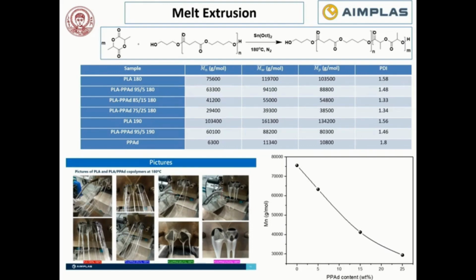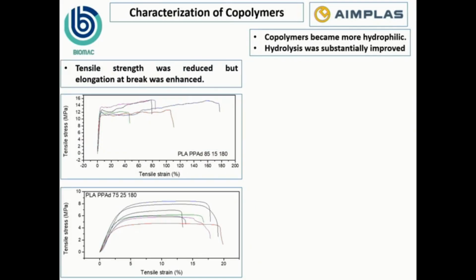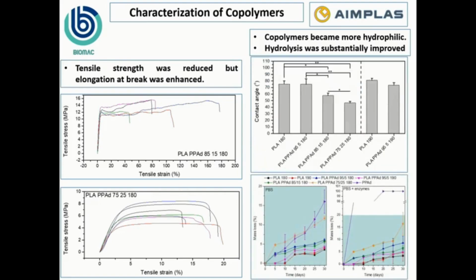In the copolymers, as the amount of polypropylene adipate increases, there is a slight reduction in molecular weight, which was expected, but we succeeded to increase the elongation at break. PLA breaks with an elongation of about 2 to 3%. Here you can see that by using 15% of polypropylene adipate, we succeeded to get films with more than 120% elongation at break. And as I said, we want to see if we can produce biodegradable polymers. You can see here the molecular weight reduction, which is much higher in the copolymer.